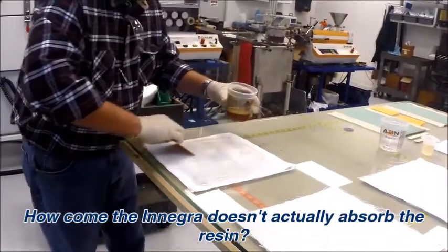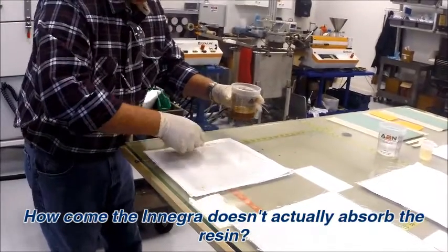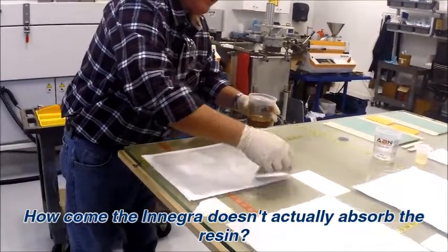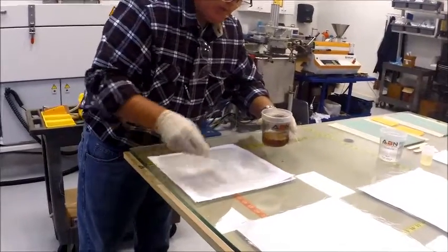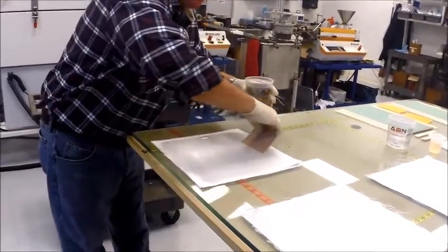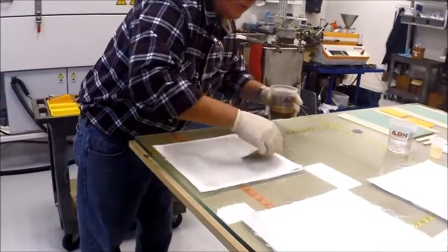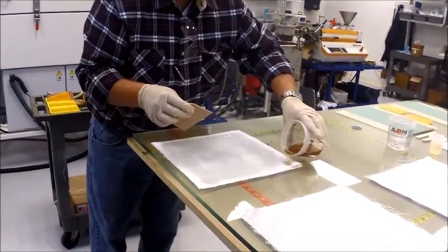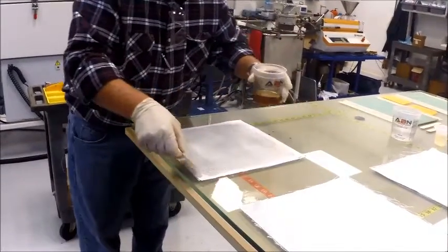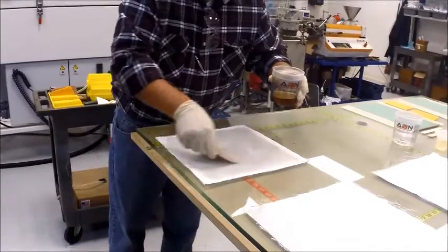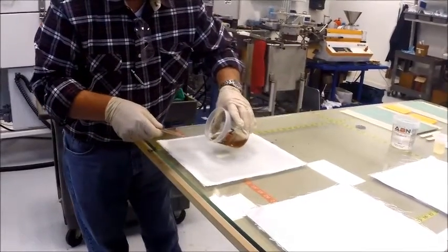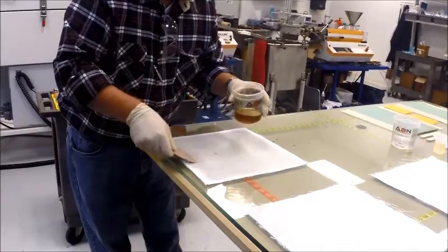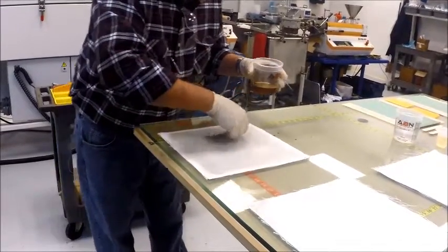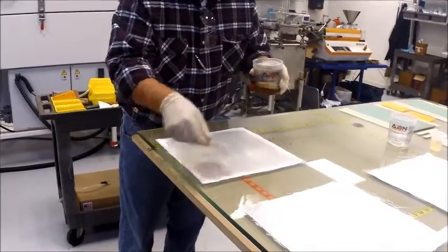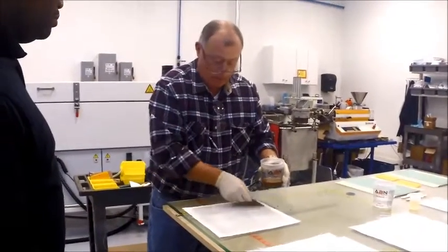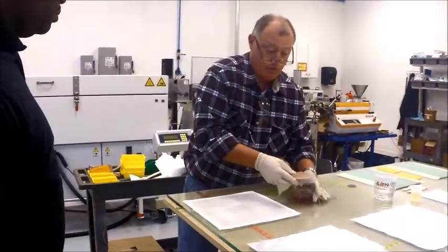Russ, how come the Innegra doesn't actually absorb the resin? It's a hydrophobic fiber, and that means it won't absorb any resin, it won't absorb any chemical. So we have to try to encapsulate it in order to trap it in the laminate. This particular resin system here, without getting into the make of the resin system itself, I've found to have phenomenal adhesion properties with the Innegra. So less resin in some cases can be achieved depending on the resin system that you select and how it's compatible with the Innegra that you use in your laminate.